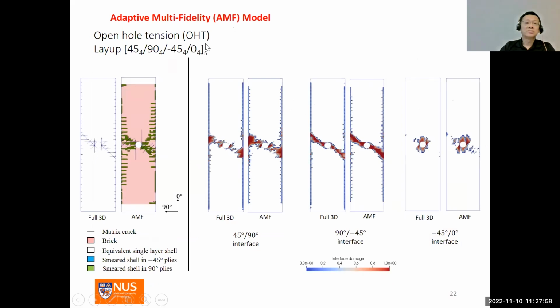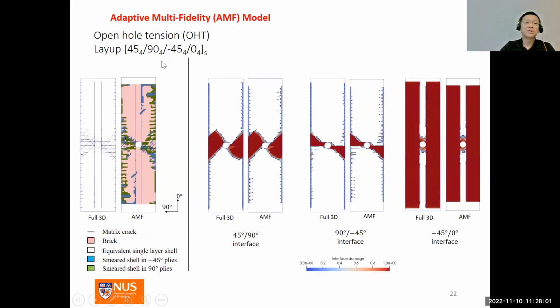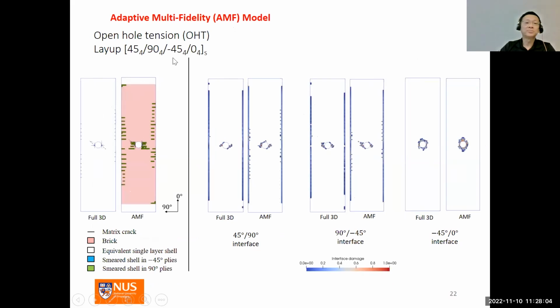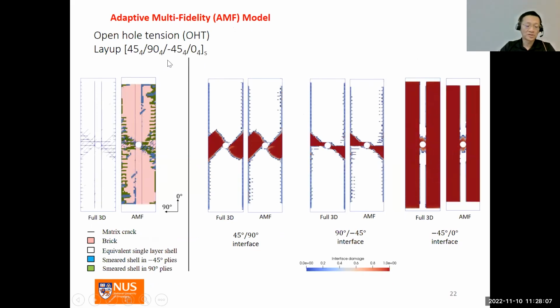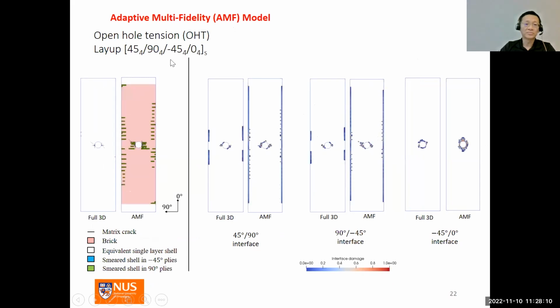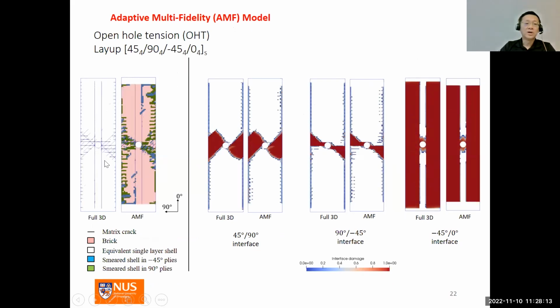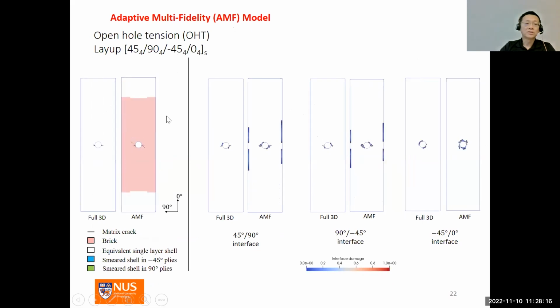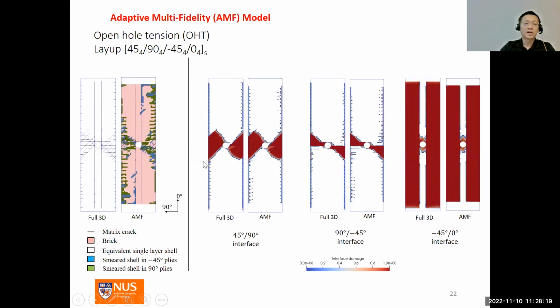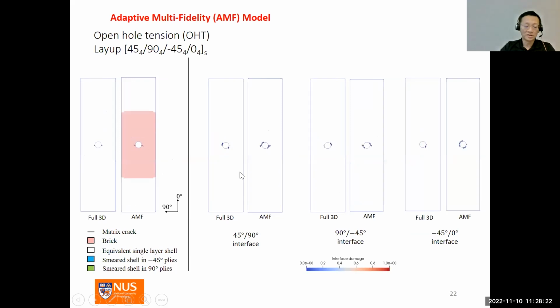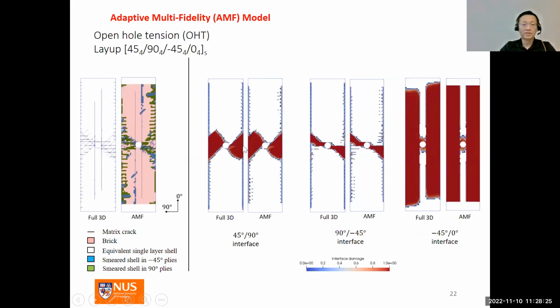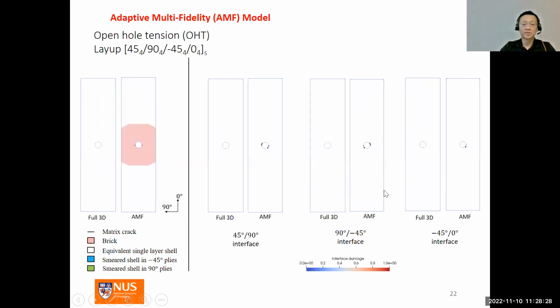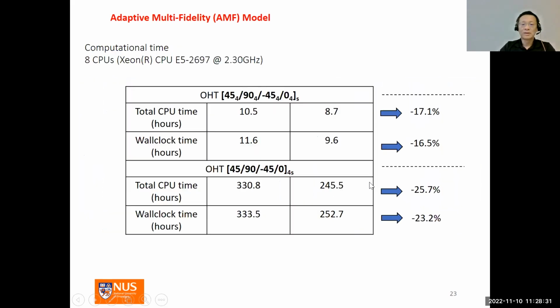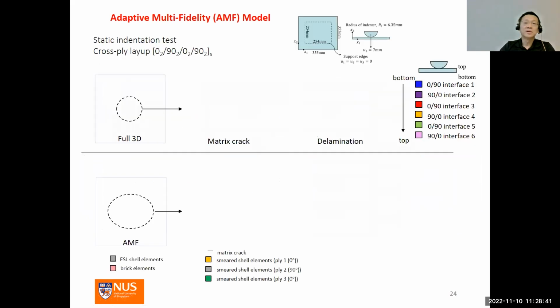This is a similar OHT specimen, except with blocked plies. So there are 4 of each ply here, like this. And this kind of specimen has a greater tendency to delaminate. So in addition to modeling the matrix cracks, you actually can predict the delamination growth at the various interfaces as shown in the pictures with the red regions here. So there can be further savings of maybe about 20% in computational time.